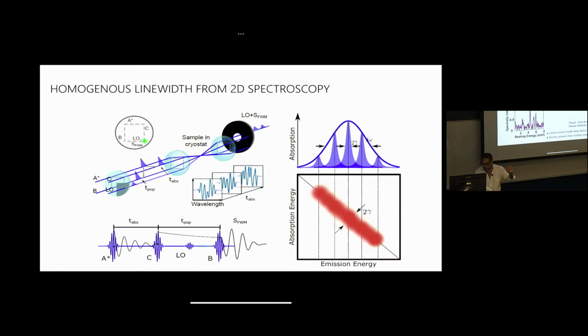So that's one story I'm not going to show you, but what I am going to show you is another experiment in which we're now going to the type of question that we're interested in for the optical microcavities. Let's say that we have an exciton here and there's an exciton there. If I'm in the microcavity, we're going to couple strongly to the photon to form so-called exciton-polaritons. We're going to scatter and exchange momentum, and that feeds a new ground state that is at a particular density, below a particular temperature. It's going to form something akin to a Bose-Einstein condensate, perhaps not in equilibrium, but something like a condensate. So the mechanism for that is exciton scattering. Now, if I'm exciton A and my colleague there is exciton B, we perceive the lattice in a very different way. How does the fact that we're dressed by the lattice differently affect the scattering? So that's what we're going to focus on right now.